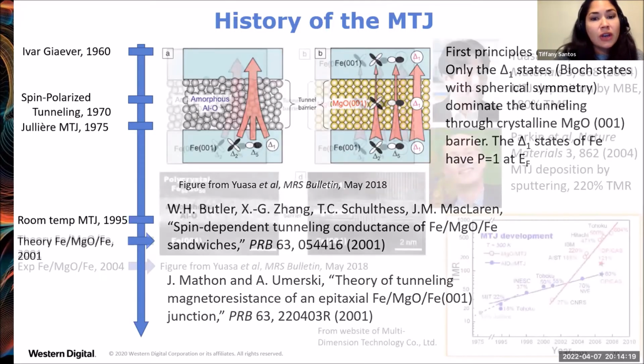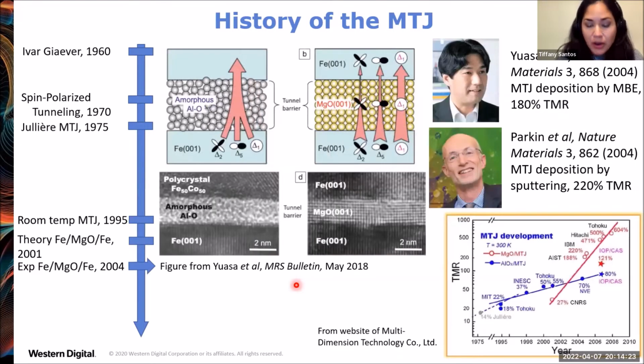And just a few years later, it was confirmed experimentally: very high TMR from magnesium oxide tunnel barriers with iron electrodes. And this was shown and published in the same journal edition of Nature Materials from Shinji Yuasa, showing TMR of 180%, and Stuart Parkin showing 220% TMR for MgO barriers. And over time, there have been improvements to the structure and TMR has increased. And now today we can see over 600% at room temperature for MgO barriers. This is a lot higher than what you can see with amorphous aluminum oxide tunnel barriers, which reaches around 80%, certainly staying below 100%.